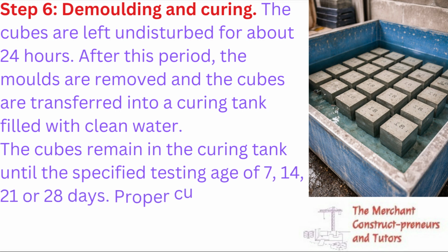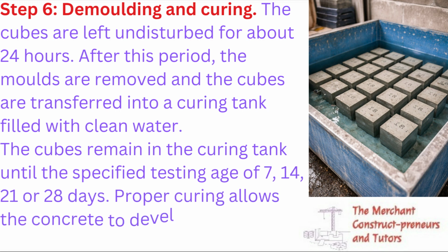So the next step is to what? Demolding and curing. Now the cubes are left undisturbed for about 24 hours. After this period, the molds are removed and the cubes are transferred into a curing tank filled with clean water. Now the cube remains in the curing tank until the specified testing age of 7, 14, 21 and 28 days is reached. So it depends on when it is time.